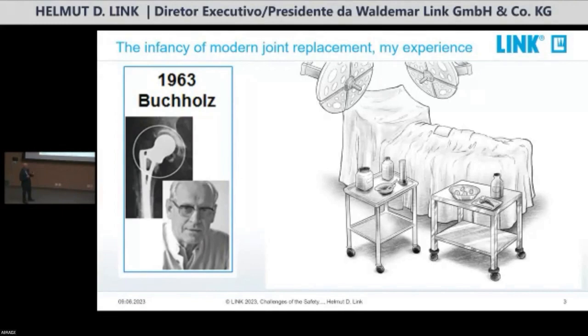The bone cement came from a bottle with powder, the polymer, and a bottle with the liquid, the monomer. So they took the powder, they took the monomer, and they mixed it. And that was autosterile, because it generated heat. So they told me the heat sterilizes it. So that was how the original joint prostheses were implanted. The first joint prosthesis Buchholz implanted in Germany was in November 1963.